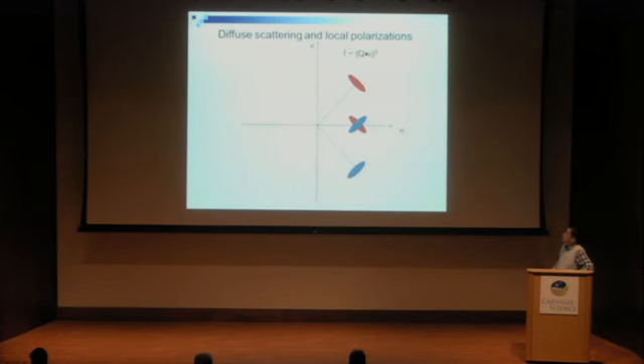And in neutron diffuse scattering, the intensity is proportional to Q times u, the atomic displacement, squared. So the red wing here, around the 110 Bragg peak, should mainly come from local polarization along the 110 direction. And the local polarization along the 1-10 direction will contribute to diffuse scattering along the 1-10 Bragg peak. And near the 100 Bragg peak, they have contributions from both the red and the blue wings.